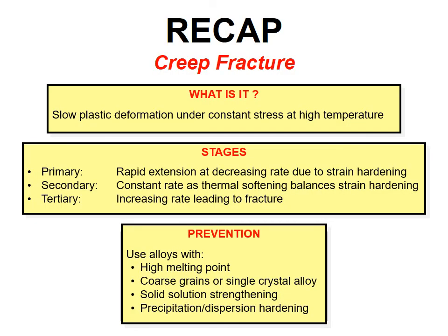Before we end this topic on creep, let's recap. Creep can be defined as a time-dependent plastic deformation that takes place under a constant stress at elevated temperature. Its deformation shows three distinct stages, where primary creep shows rapid extension at a decreasing rate due to strain hardening, followed by secondary creep, which proceeds at a constant rate as thermal softening balances strain hardening. This eventually leads to the tertiary stage, with increasing strain rate leading to complete fracture.